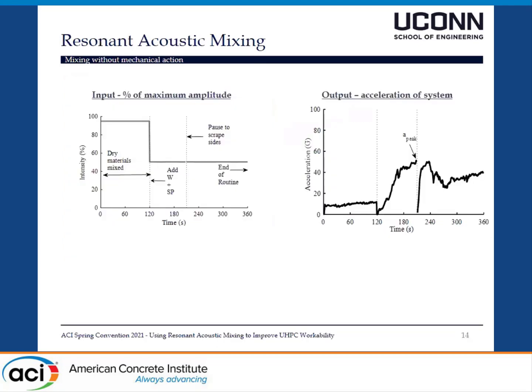And this is an example of what you could have as far as data. On the left, you see the inputs. Again, this is just intensity. Intensity means a percentage of the maximum amplitude of the pressure wave over time. And you can see within 5 minutes, the end of mix is the end of the routine. And you have the capabilities of pausing it, of mixing your dry materials at different intensities than your wet materials, et cetera. And what you get as an output, in terms of acceleration times the gravitational constant, is a peak acceleration.